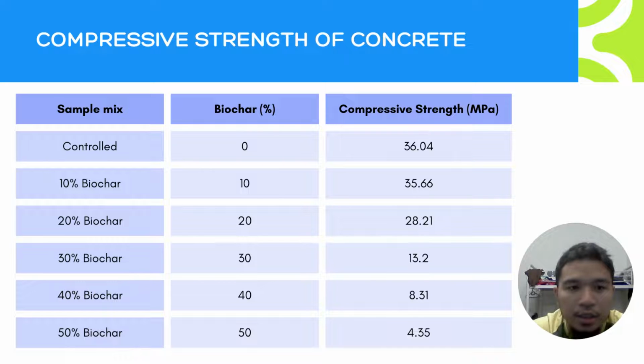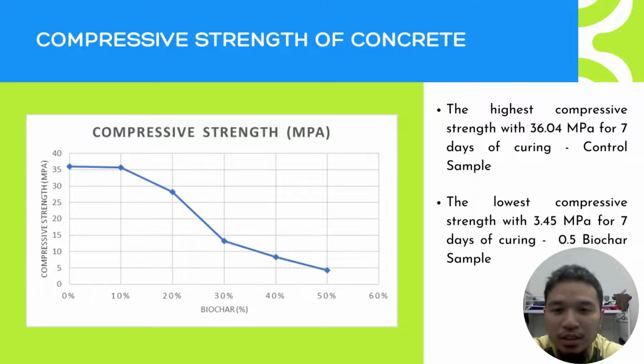So as we can see, the data show that compressive strength decreases with the addition of biochar. However, an addition of 10% biochar showed almost the same strength as standard concrete. So we choose 10% biochar as our optimal ratio for our lightweight concrete. This is the graph for the compressive strength. As we can see, the graph decreases.